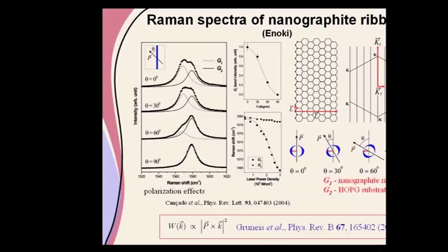And this is just to show you that Raman spectroscopy satisfies the selection rules as it might. So we have a ribbon sitting on graphite. The upper frequency is graphite, and that's the substrate. The ribbon is this one, the lower frequency. Why is it lower? You put a laser on it, and it's a very tiny ribbon. Even if you put a small amount of energy, it gets hot because the C-axis thermal conductivity is very poor. So it has very poor contact. So laser energy heats it, and that's what produces the downshift. So we can tell them apart, which is nice.